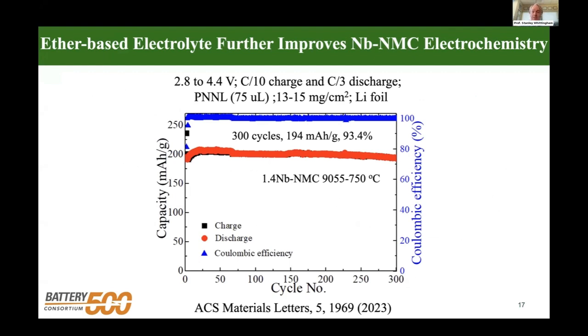Here's now showing similar data, but in this case, we've now switched away from the carbonates to the ether-based electrolytes, following the PNNL protocol. And you can see we're now getting quite a bit higher capacity, over 200 compared with 180, and there's very little capacity loss. So we're getting essentially 100% Coulombic efficiency at realistic loadings.